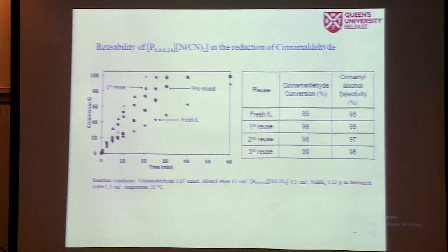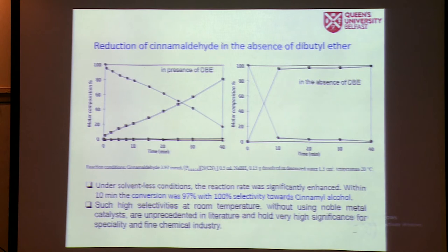So this is a solvent-less study, just in the presence of ionic liquid without any dibutyl ether. The reactions are even faster. Within 10 minutes, we can go to 100% conversions with 100% selectivity to cinnamyl alcohol.